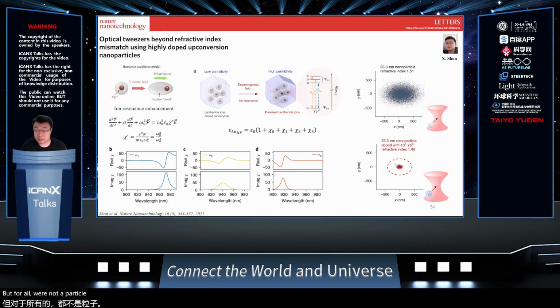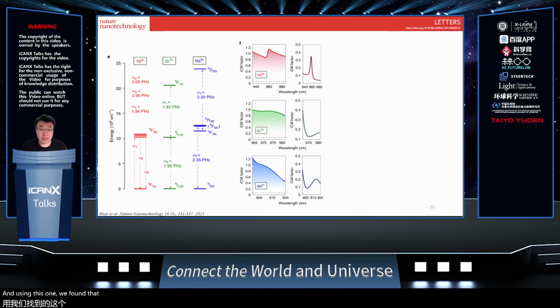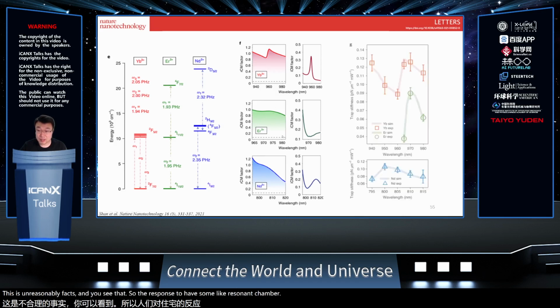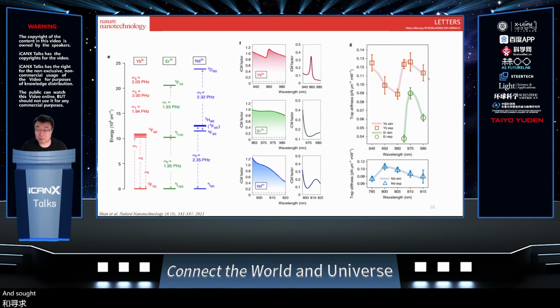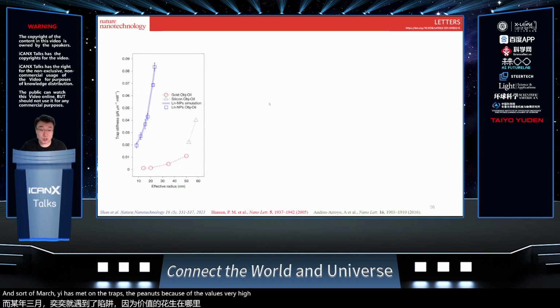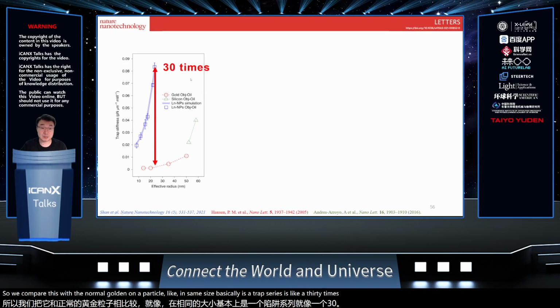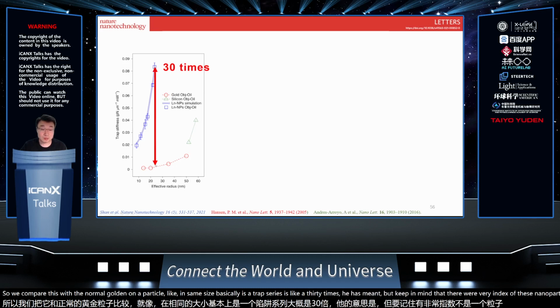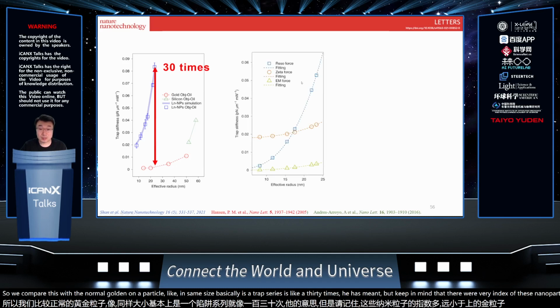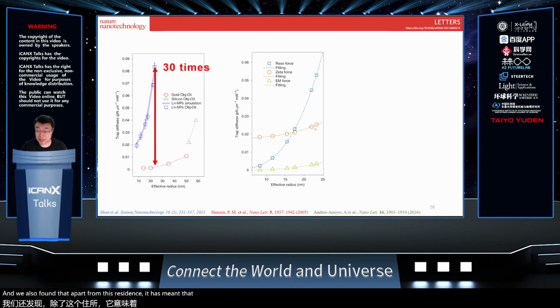But for our nanoparticle, benefiting from this ion resonance effect, the trap stiffness is really high, so the point distribution is really dense. Using this, we found that for all kinds of lanthanide ions we have this ion resonance effect, and you see that the response has a resonant shape. Experimentally, we scan different wavelengths and see the trap stiffness vary, with much enhancement because those values are really high. We compared this with a normal gold nanoparticle of the same size, and the trap stiffness got 30 times enhancement, keeping in mind that the refractive index of these nanoparticles is much smaller than the gold nanoparticle. We also found that apart from this resonant enhancement, the zeta potential also gave some enhancement.